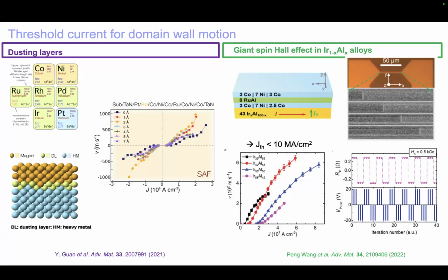And it turns out we discovered in these materials that by tuning the composition, let's say in this case of iridium and aluminum, we can increase the resistivity by a factor of 10, and this leads to enormous spin-dependent scattering, leading to enormous values of the so-called spin-Hall angle, which is the ratio of the number of spin-polarized electrons created for every electron in the current. And this leads to, again, reduced threshold current densities, because the larger the spin-Hall effect, the more efficient is the motion of domain walls and the torques that can be applied.